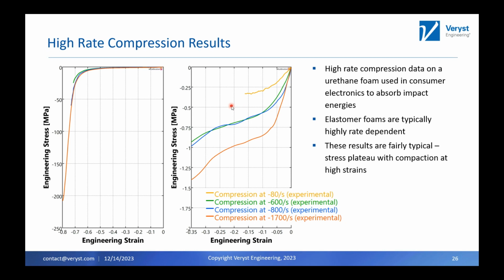Being able to test these small foams is important because you may not be able to get them thicker, or depending on the manufacturing process, their properties are going to change with the thickness. Some of these foams have what are called carrier layers on either side, and the carrier layers might be 10 micron thick polyethylene or polypropylene or something like that. So, a foam that's 50 microns versus 200 microns is going to have those same carrier films. So in the average sense, you're going to have more of those backer films in the thinner materials, and you're probably going to see a stiffer behavior and quicker compaction. So making sure you test your right thickness is going to be very important.